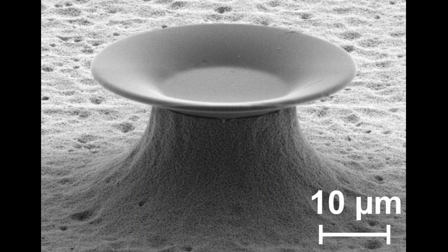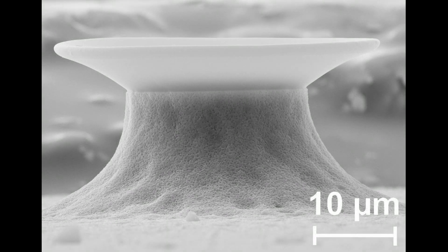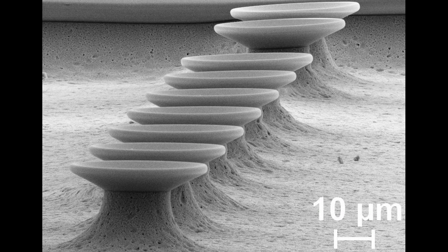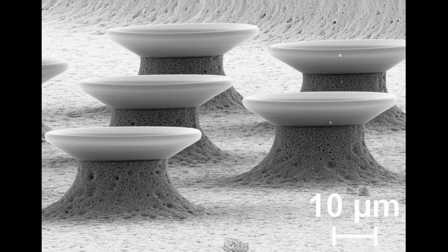The conical polymeric micro-resonator is an optical device fabricated from polymethyl methacrylate, commonly known as PMMA. It is fabricated by electron beam lithography and etching. Conical polymeric micro-resonators are optical resonators which exhibit an exceptionally large quality factor in the order of 10 to the power of 6 due to their very smooth surface. This property allows for a variety of applications, especially for biosensing and lab-on-a-chip devices.